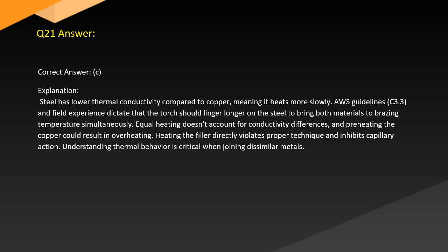Answer. Correct answer: C. Explanation. Steel has lower thermal conductivity compared to copper, meaning it heats more slowly. AWS guidelines C3.3 and field experience dictate that the torch should linger longer on the steel to bring both materials to brazing temperature simultaneously. Equal heating doesn't account for conductivity differences, and preheating the copper could result in overheating. Heating the filler directly violates proper technique and inhibits capillary action. Understanding thermal behavior is critical when joining dissimilar metals.